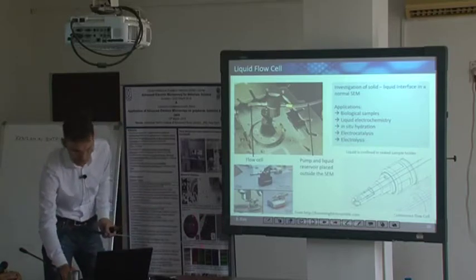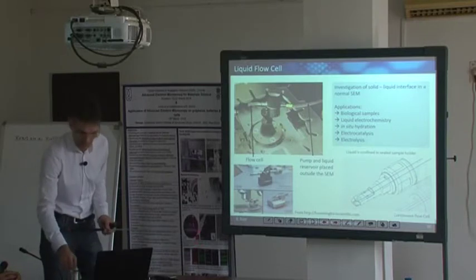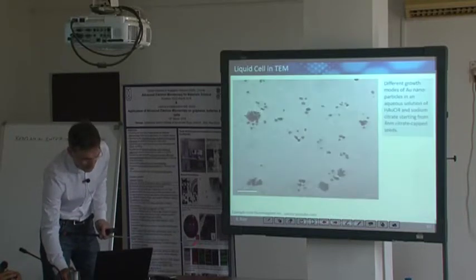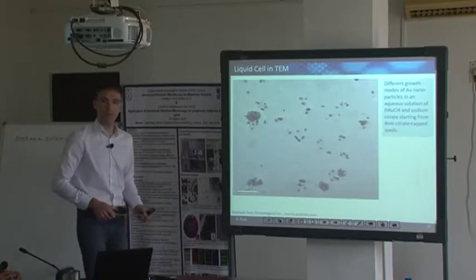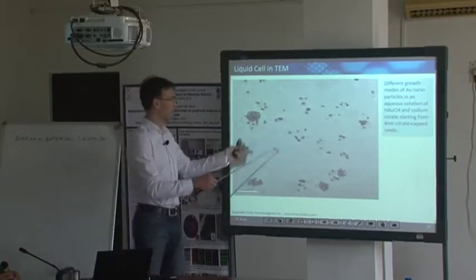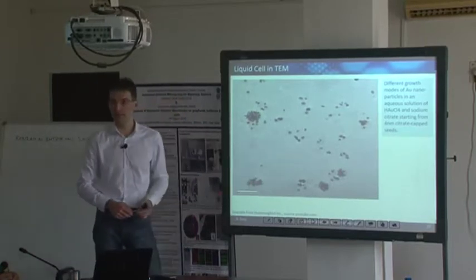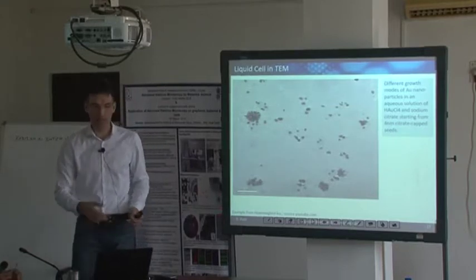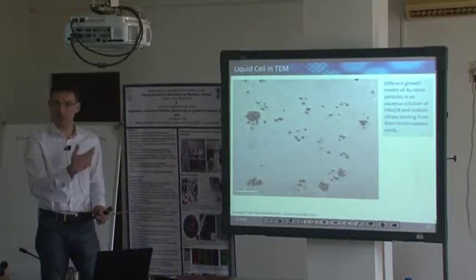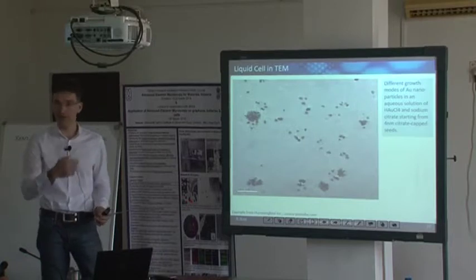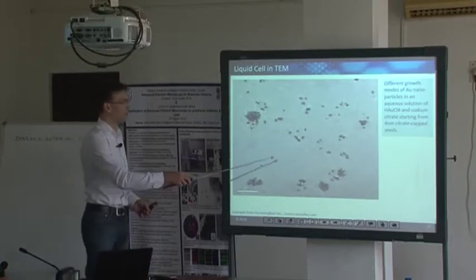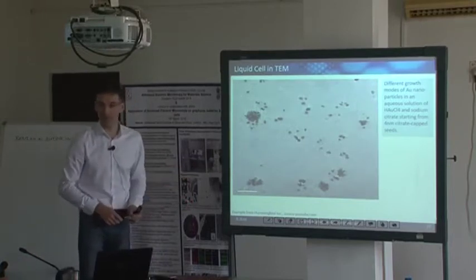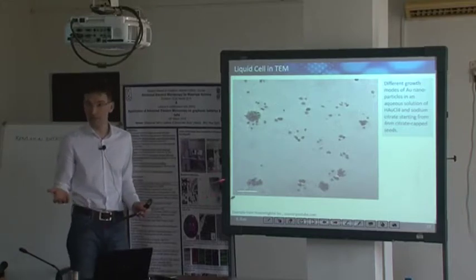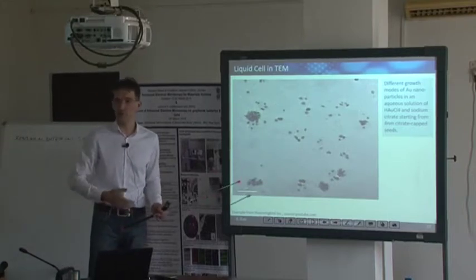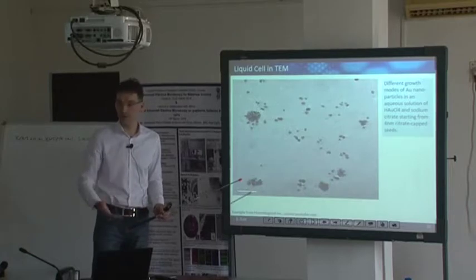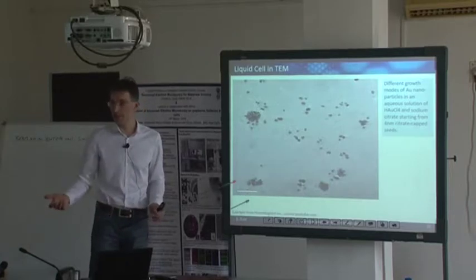within this liquid environment. And as I mentioned already, you have to think about how the electron beam affects this liquid phase, for instance, because you can easily imagine that you ionize all those species because you have the interaction not only with your sample that you're interested in, but as well with your liquid environment, and by that you might change, for instance, the pH of water. Because you introduce ions, the ion concentration is higher, by that the pH is different.